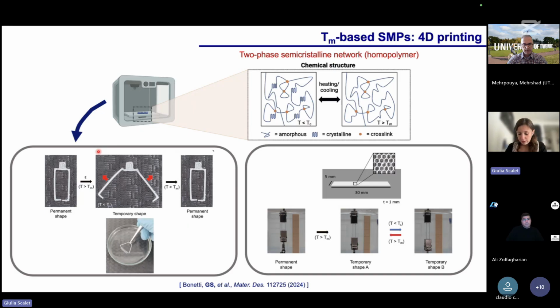We printed for the first time these materials with an extrusion-based approach. I will not enter into the detail of the chemistry of the material. This is for a PCL-based semicrystalline network. So it is just one polymer, but this technique can be extended also to other types of networks. And we use extrusion-based printing with UV cross-linking during printing. And we were able to manufacture different types of actuators that are based on the one-way memory effect and two-way memory effect with different designs.